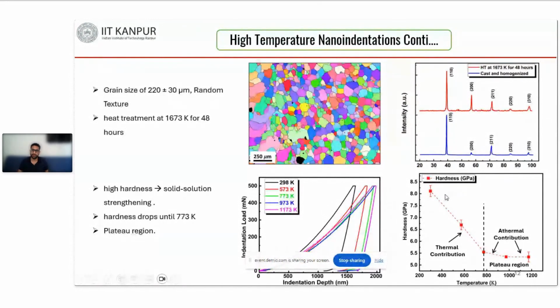If you see this behavior as a function of temperature, it has 2 stages. Initially, from room temperature 298 Kelvin to 773 Kelvin, there is a steep drop in the hardness value, and then there is almost temperature independent behavior. This steep drop can be a result of an activation barrier for the movement of edge and screw dislocations from a locally favorable region. Thermal assistance helps to move the dislocations from their locally favorable region. That's why there is a steep drop in this value.